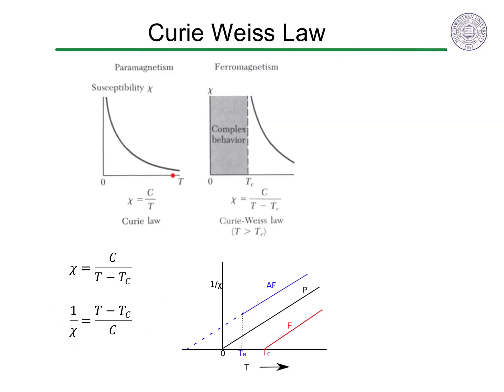To summarize, the Curie law describes well the magnetization of a paramagnet as a temperature-dependent susceptibility that increases as T approaches zero, like a Curie-Weiss law with Tc equals 0. The Curie-Weiss law is used to describe the behavior of ferromagnetic materials when they are in their paramagnetic regime at high temperature, above the Curie temperature. As the temperature is lowered to Tc, the susceptibility diverges because the magnetization becomes large even with a small magnetic field.